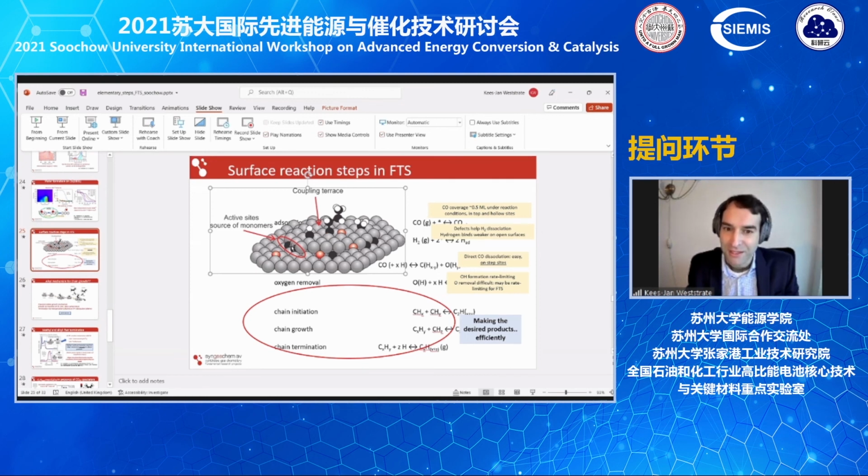And then the nice thing is you will have many edges on a single terrace. So all of these edges can, at a very slow rate, make your monomers, but all those monomers will go to the same terrace. So you will have very many monomer-making sites that can work together, because all the monomers come together on this single terrace where the growth can happen.